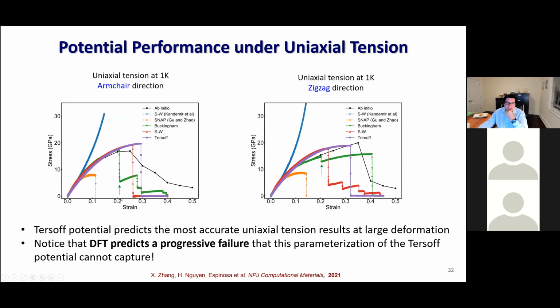And more importantly, the stress-strain curve, this is the DFT data. The Tersoff is not perfect, but you can go with confidence to 20% deformations and even predict peak stress and the failure for the two directions, armchair and zigzag. And this is what I started with. The others were very poor. Even Buckingham, which is a very elementary potential, predicts good nonlinearities, but it gives some artificial phase transition, because of obviously limitations of the potential.